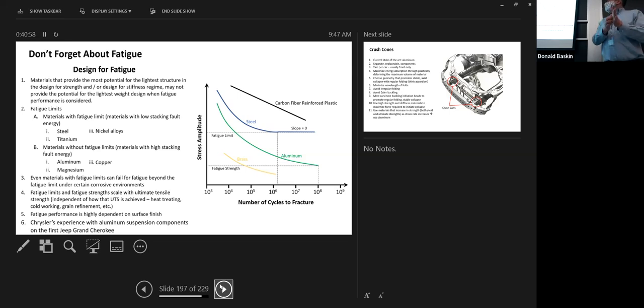And some materials, if they have a low stacking fault energy, they tend to have a fatigue limit. If they have a high stacking fault energy, they tend not to have a fatigue limit. So steel has a fatigue limit, nickel alloys have a fatigue limit, titanium has a fatigue limit. That's one of the things that makes it good for bicycles. But aluminum, copper, brass, magnesium, especially magnesium, those materials don't have fatigue limits. There's always some combination of stress and cycle where they're going to fail.